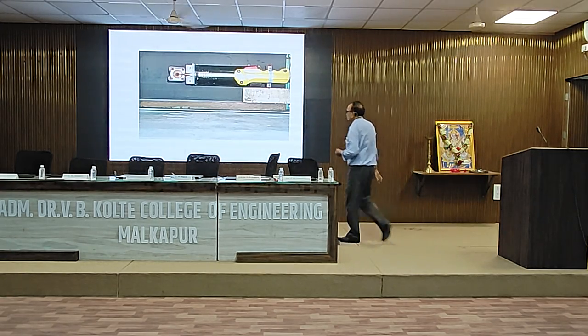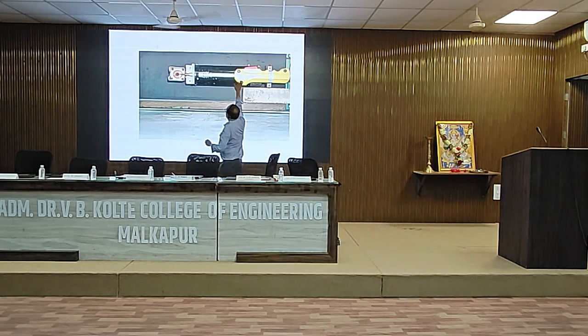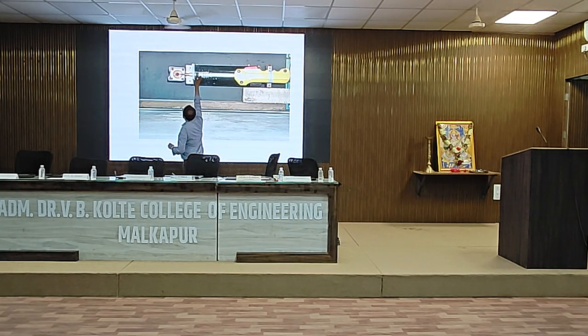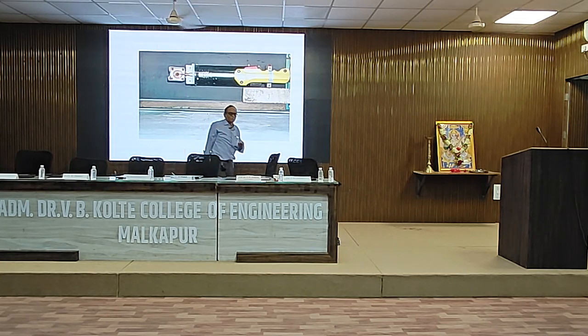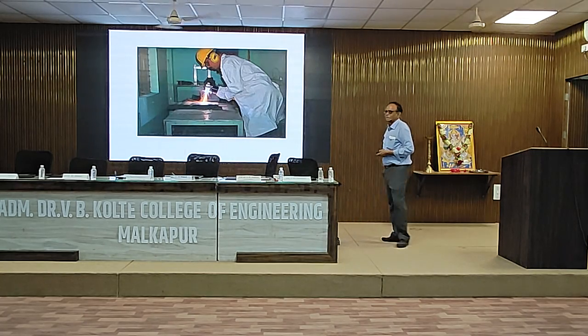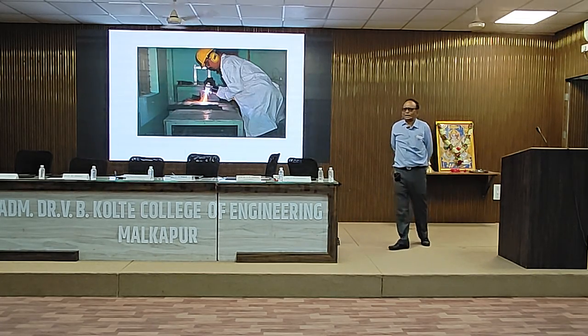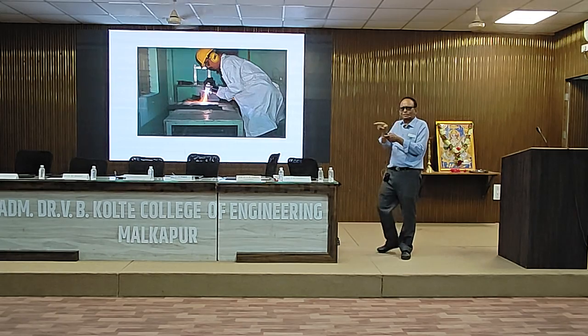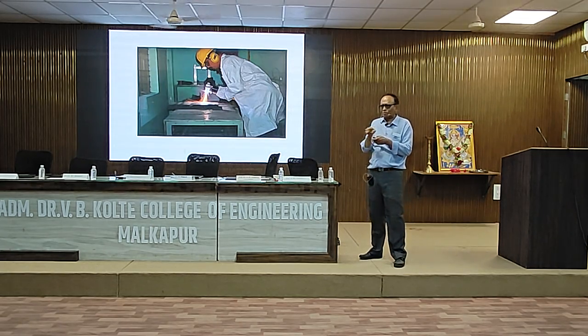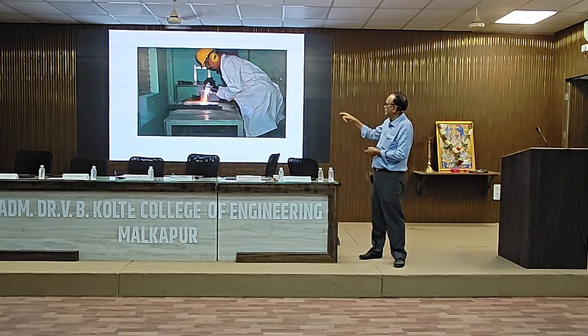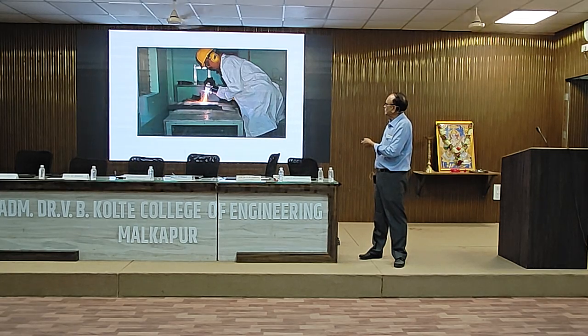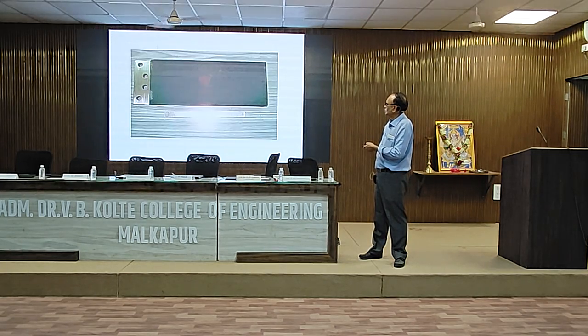This is one electrode which is feeding the metallic wire, and this is another, water-cooled electrode. An arc is struck between the two, and at the base of the arc, the temperature is very high. So basically, you see something like this. And now into that arc, you feed the metallic wire continuously. It will undergo melting, and by the splats, you can form the coating very easily.